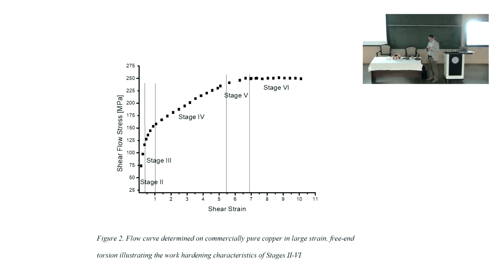This was done in a torsion test, which is a simple shear process, unless during torsion the bar is changing length - there are some length changes if you twist a bar, a small second-order effect. Here only the shear strain is shown, and shear flow stress at the outer surface. This was a bar, so this is a large strain experiment, and you can see that one can identify up to 6 stages. But stage 1 is not there - it begins with stage 2, because I am classifying the different stages as it is done for single crystals. But in single crystals, usually you do not get to such a strain, so there are additional stages.